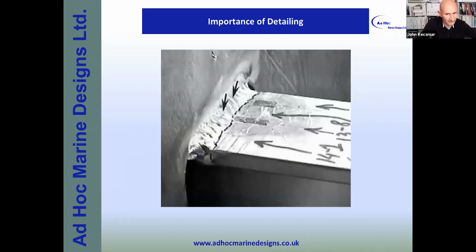If we take that one stage further, here we have what is a T-bar, but it's actually longitudinal, and it's passing through a transverse frame. For whatever reason, the designer decided to specify welding the flange of the T directly to the web of the transverse frame. But if we start to analyze this, why did he do this? Well, I suppose really when you consider what is the objective of it, and quite clearly it can only be to transfer the shear load from the longitudinal into the web.